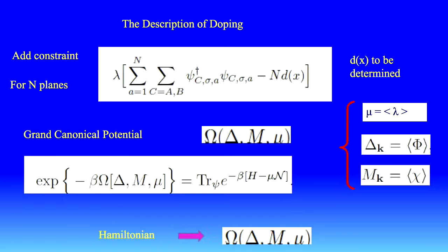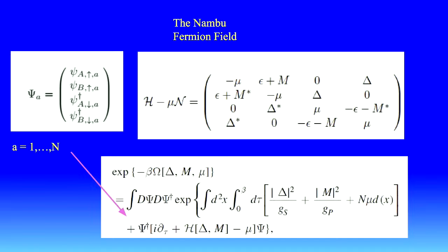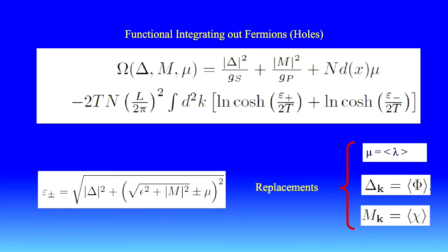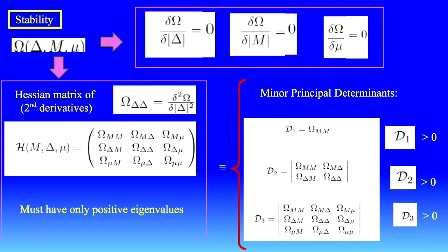But we have been very careful. So this is just rewriting using the Nambu fermion field. I obtain this. So if I integrate over the fermions, I have this expression with these eigenvalues. So this is my grand canonical potential. Now, in order to justify that mean field, we've been very careful about stability. You see that, for example, the first derivatives must be zero, and the Hessian matrix of the second derivatives must have only positive eigenvalues.